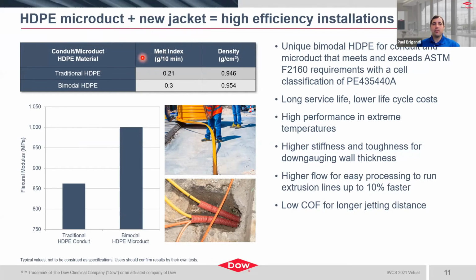So really what we compare here, more tailored toward the conduit space itself, is this new bimodal high density polyethylene, so looking at higher flow and also higher density material. In this case, what we can do is provide improved processability as well as improved performance, so higher stiffness and toughness as we look to down gauge. So with the higher density, this higher flexural modulus, the new bimodal materials, while maintaining excellent processability to meet these ASTM cell classifications, we're able to achieve that and provide long service life and really lower life cycle costs,